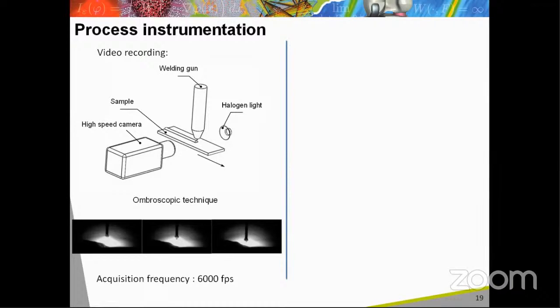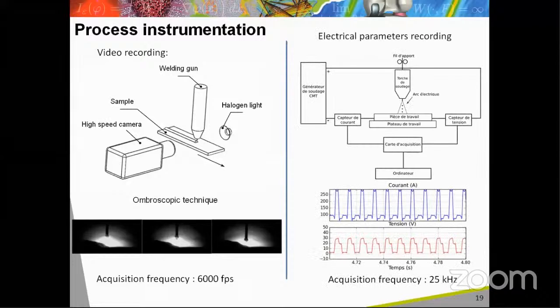In order to study the stability and the regularity of these phenomena according to the process parameters, two kinds of data are recorded during the process. Video recordings are obtained using a high-speed camera. A shadowgraphic technique has been used to observe the deposited metal shape through the electric arc. For that, a halogen light is placed behind the wire tip that allows observing the contour of the deposit despite the arc radiation. In addition, the electric parameters, voltage and current, are recorded with a high acquisition frequency to follow the stability of the different phases of the CMT cycle.